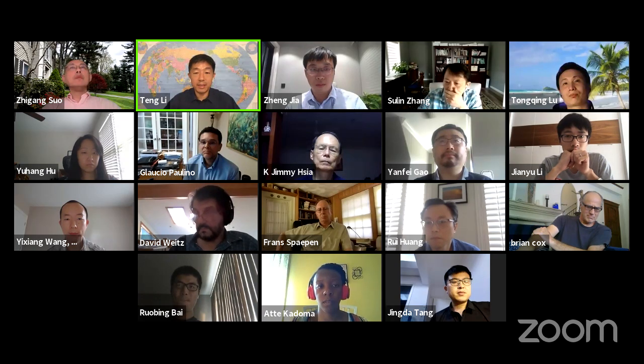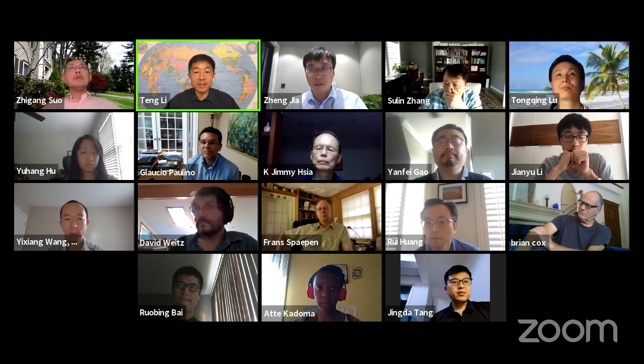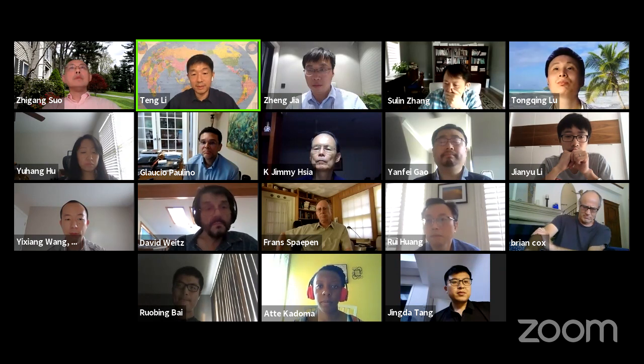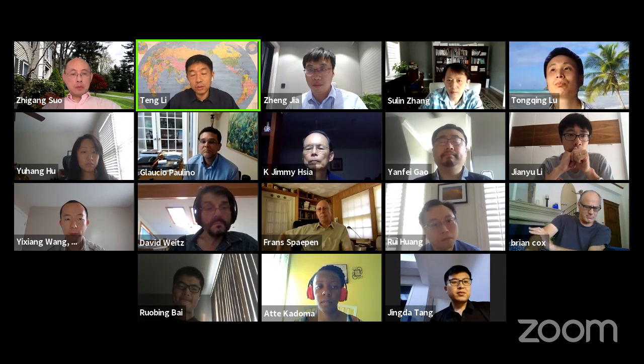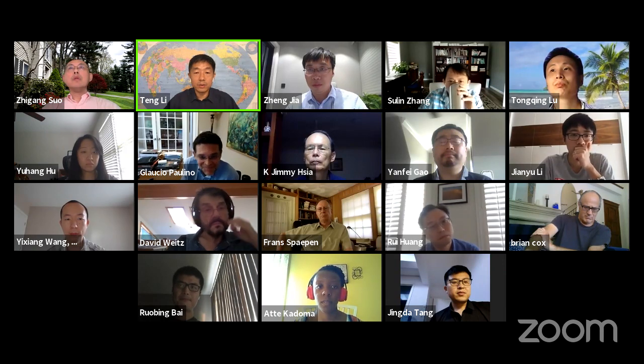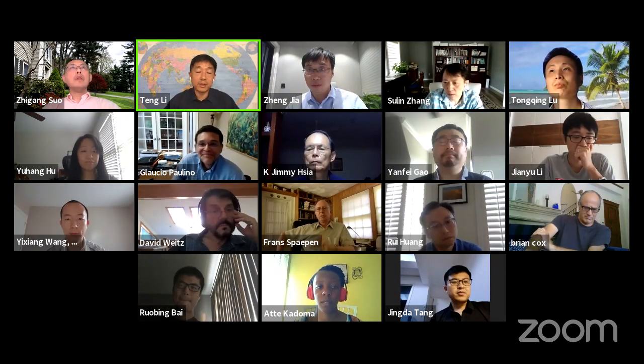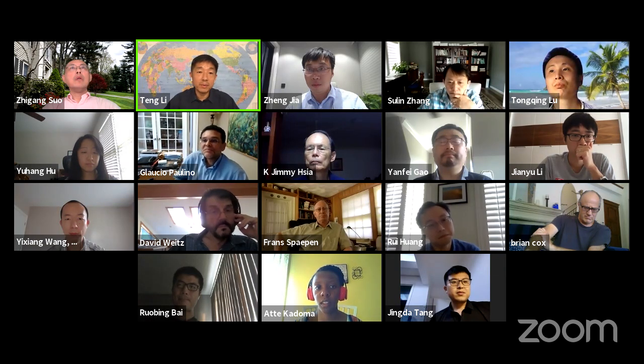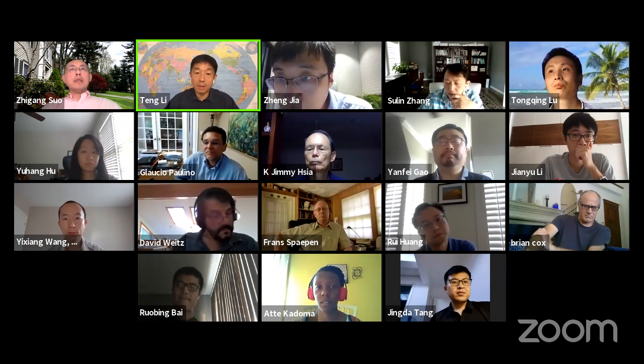Okay, so I actually showed in the slide. So for the densified wood, it's actually still quite brittle. I think that's one of the drawbacks we have. It increased the strength of the natural wood a lot by 10 times, 11 times, but it doesn't increase the ductility much. And sometimes it's even slightly lower, but natural wood, the ductility is low anyway. So this is one of the drawbacks it has in comparison with, for example, steel, aluminum, they are actually very ductile. So this is also something we are trying to improve or overcome now.